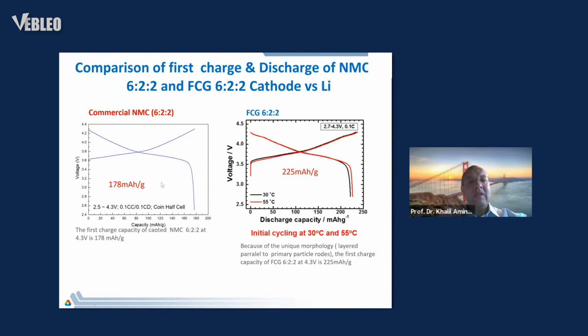This is a charge-discharge curve of both commercial and FCG. You can see when we operate at the same condition at 4.3 volt, we had about 180 for the conventional. We had about 225 for the FCG because of that unique morphology that I just showed you.